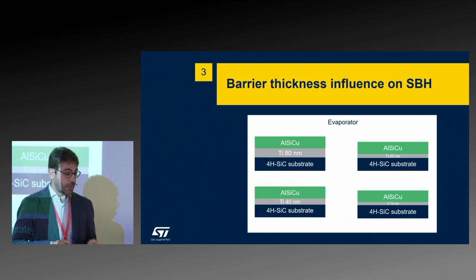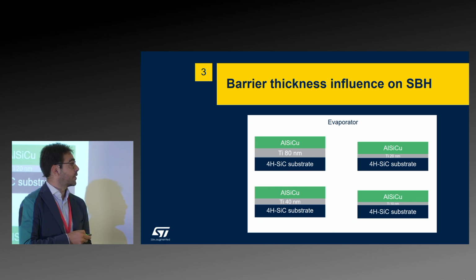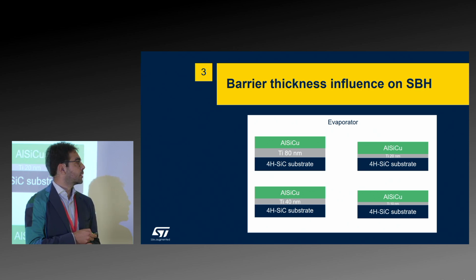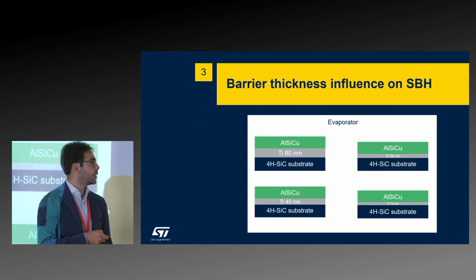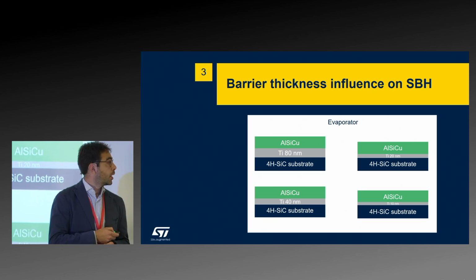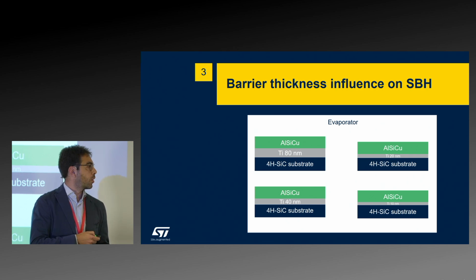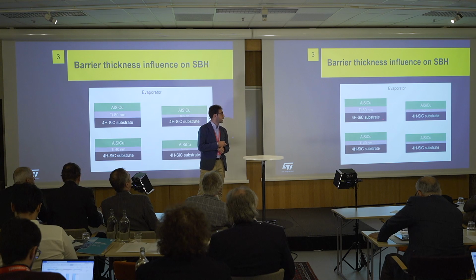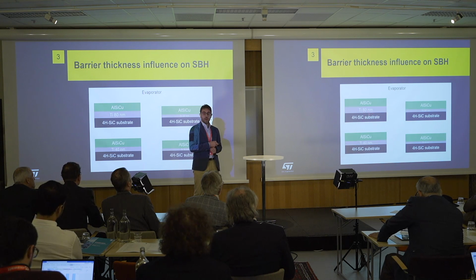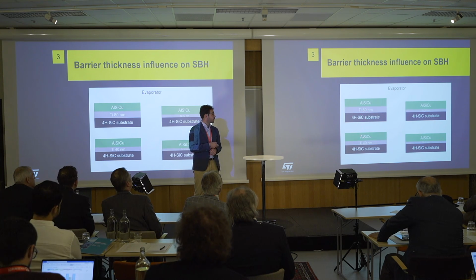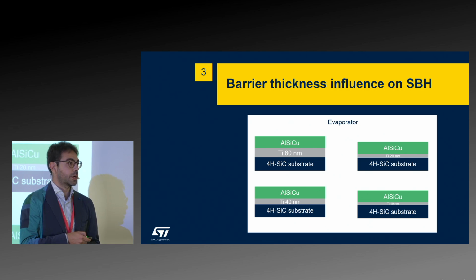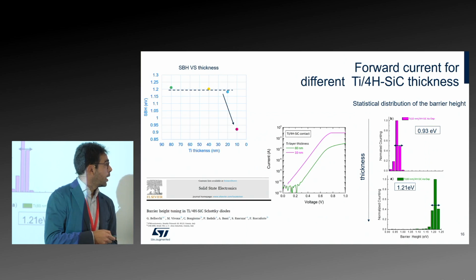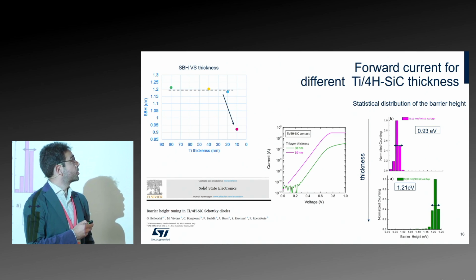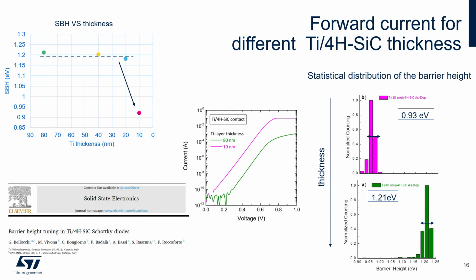Another approach that we used is starting from our traditional device that I told you about: 4H SiC, 80 nanometers of titanium, and an aluminum compound just for the contact. We change the titanium thickness from 80 to 10, crossing 40 and 20 nanometers. And what we observed, looking at the Schottky barrier height, is that for all the thicknesses from 80 to 20, the Schottky barrier height doesn't change.